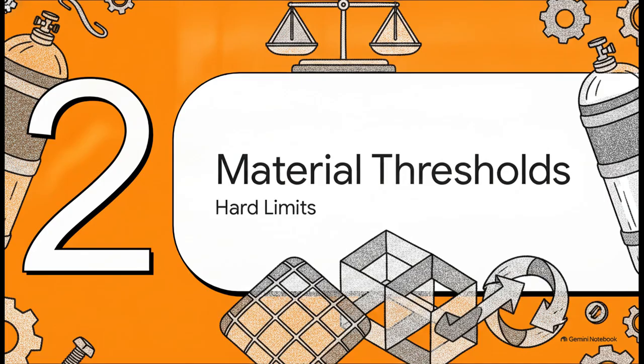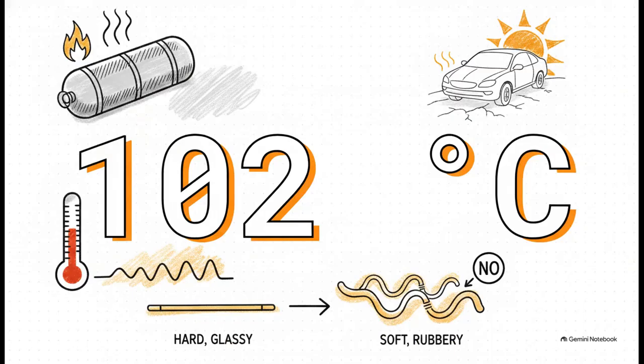Moving right along to Section 2, material thresholds. These are the hard limits. Okay, the big takeaway here is the glass transition temperature of the resin material. Tested under ASTM D3418, it absolutely cannot dip below 102 degrees Celsius.